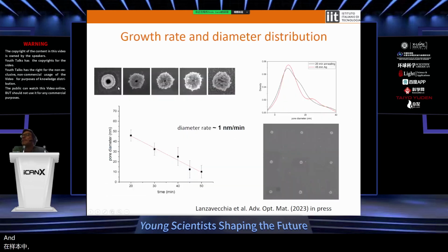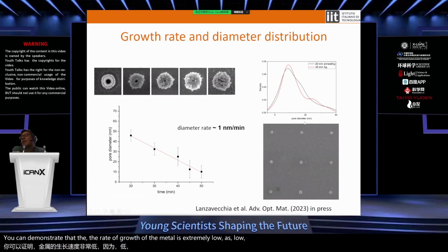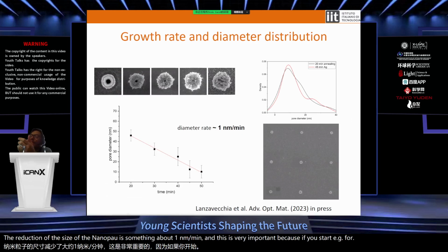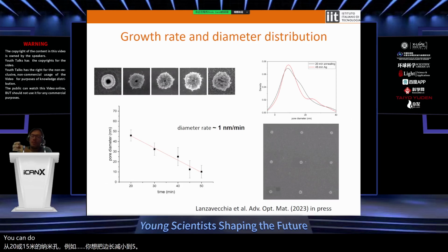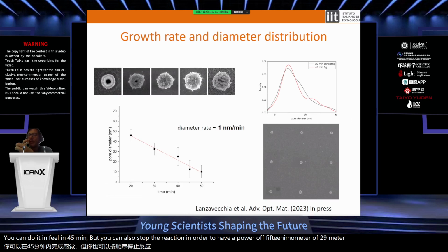And another important aspect is that if you perform the same reaction with increasing duration, you can demonstrate that the rate of growth of the metal is extremely slow. The velocity of the reduction in size of the nanopore is something about 1 nanometer per minute. And this is very important, because if you start, for example, from a nanopore of 50 nanometer, and you want to decrease the size down to 5, you can do it in 45 minutes, but you can also stop the reaction in order to have a pore of 15 nanometer, of 20 nanometer, or whatever in the middle.